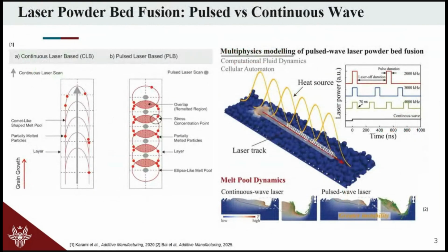Nonetheless, also dealing with laser powder bed fusion, we have several sub-technologies. For instance, changing the way the laser is emitted can alter the overall melt pool dynamics and the overall generation of defects inside a component. Indeed, the laser emission can be, for instance, pulsed or continuous. As you can understand, if the overall melt pool dynamics changes, also the fatigue behavior might change.